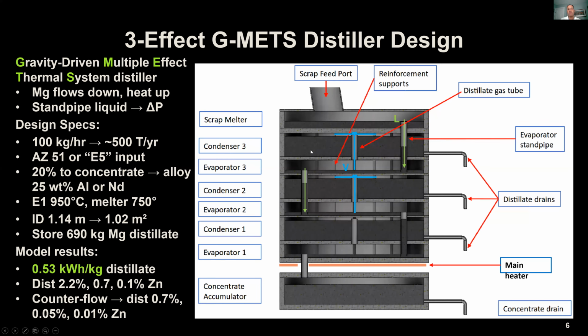So the condensers are shown here full of liquid magnesium until finally the concentrate with high solute concentration goes into the concentrate accumulator here at the bottom. The pressure difference and boiling point difference in this process is created by liquid height in these standpipes. So the lower evaporator and condenser are at higher pressure given by rho g h, density, gravity, and height, than the one above it, and therefore they transfer their heat upward. The energy use for even this 3-effect distiller is more than 90% lower than today's magnesium distillation processes and 60% lower than the vaporization enthalpy of magnesium.